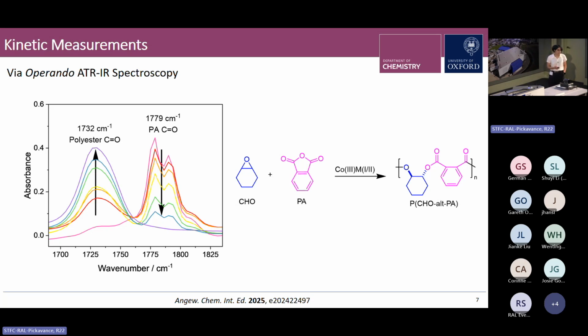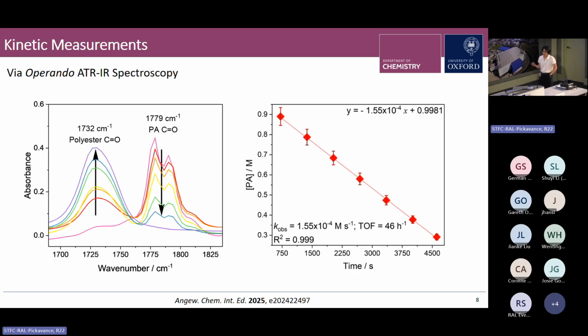We're then able to calibrate these absorbance versus time measurements to conversion or concentration versus time data by integration of an NMR spectrum of an aliquot taken at the end of the reaction. And that enables us to construct these sorts of concentration time plots. So in this case, the reaction is zero order with respect to PA or anhydride concentration, which means this plot of PA concentration versus time is linear. And then our measure of activity, our observed rate coefficient, or kobs, comes from the modulus of this gradient.